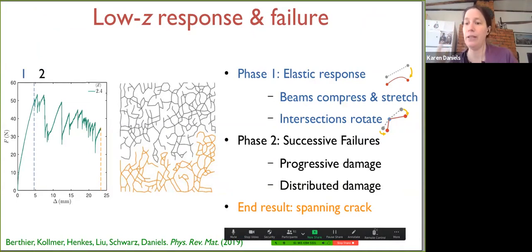And at some point, one of them will fail. At this low coordination number, that failure is progressive, right? Once it fails, it doesn't heal, and it's highly distributed. Each one of those failures is associated with a drop in the force. It fails, then it loads again, then it fails, and then it loads again, and then it fails. For the granular folks, this looks a lot like stick-slip behavior. That's a different effect, though. This results in a spanning crack eventually. The crack didn't form in one clean break, but in the end it did fail all the way across the material by some random process.